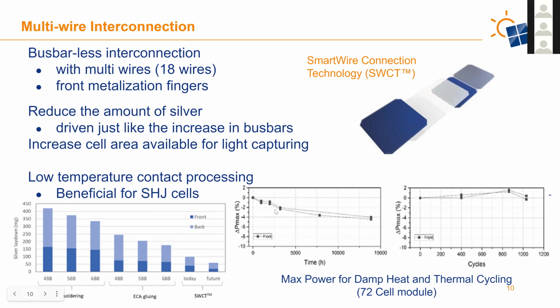What we see here is a pretty low max power drop in these 72-cell modules after damp heat and thermal cycling with these multi-wires. This was really nice preliminary work showing these are decreasing cost by reducing silver, as well as potentially increasing the power we can get out by increasing surface area, and not degrading faster.